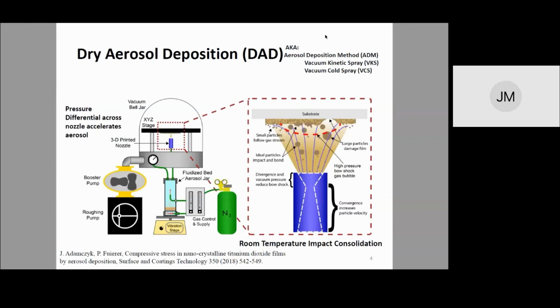And then on the right, you can see an illustration of how the powder actually consolidates on the substrates through a convergent diverging nozzle, which is the one we typically use to decrease the bow shock of the gas stream onto the substrate. This illustration also shows the necessity for the proper particle size distribution of the powder, as larger particles will impact and erode the surface, causing massive craters, while finer particles will just follow the gas stream out to the sides and not consolidate on the sample itself. Next slide, please.